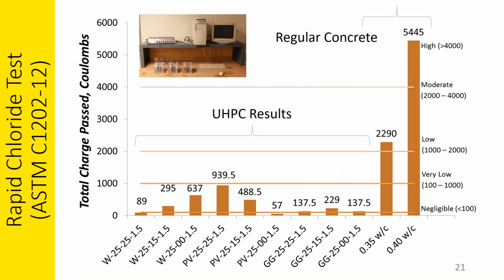This was the rapid chloride test, and it measures the charge that is passed in a slice of this material. And again, you can see the concrete on the right, 2 different formulations. And on the left, you can see again, 2 orders of magnitude less charge passed for some of the UHPC mixes that we investigated.